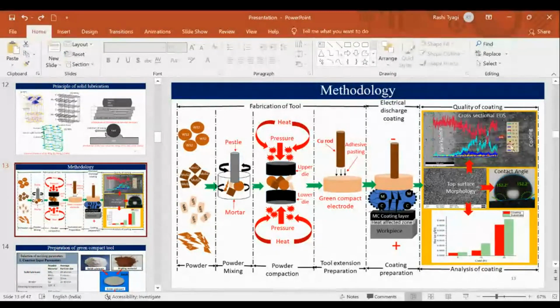Also, this is the cross section of the surface, cross section EDS of the surface. Why? To check the EDS, energy dispersive spectroscopy. It helps in checking the elements on the cross section of the surface. So to check if the material has been deposited, we also did the EDS analysis.